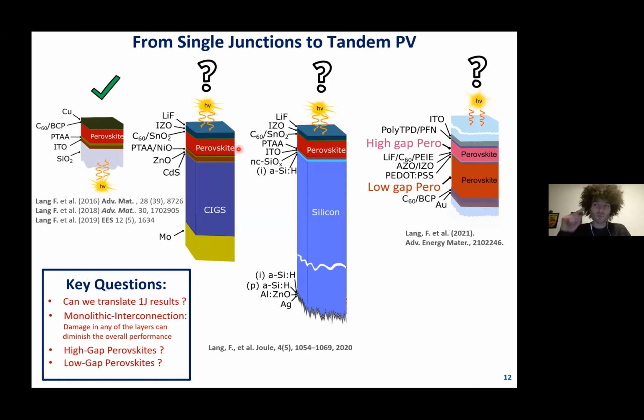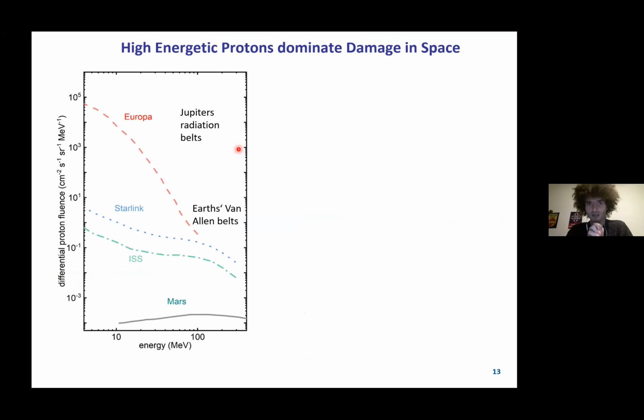Before starting into that, let's take one more step back, and I'd like to speak about the high energy particles in space. So damage is mostly dominated by high energetic protons, and there it depends in which orbit you are. So this plot here basically shows the differential proton fluence as a function of the energy for different orbits. So you have, of course, maybe heard of Van Allen belts, which we always try to stay out of. So for example, the ISS is in a relatively near orbit around Earth, still well shielded, but then some Starlink orbits are more outside, and then around Jupiter you have even higher radiation belts.